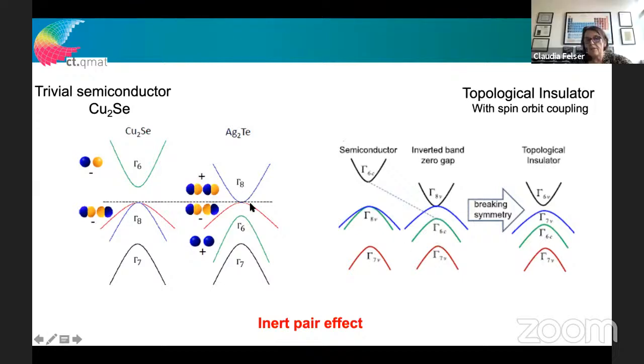Since we have this degeneracy of the gamma 8 band, which is not very good, we can break the symmetry and make topological insulators by going to tetragonally distorted compounds. Leslie is working on the zirconium silicide sulfide compounds, which are tetragonal, etc.